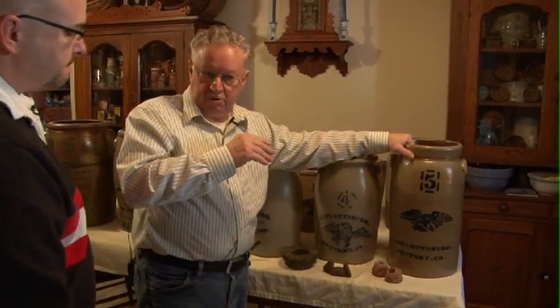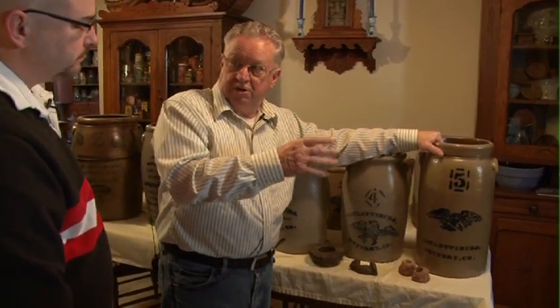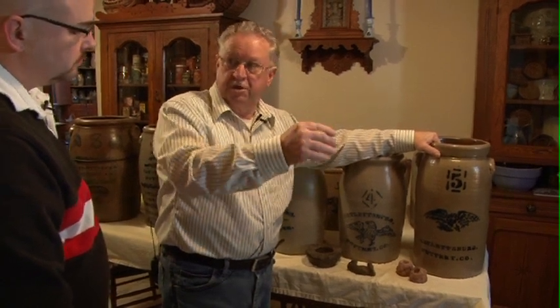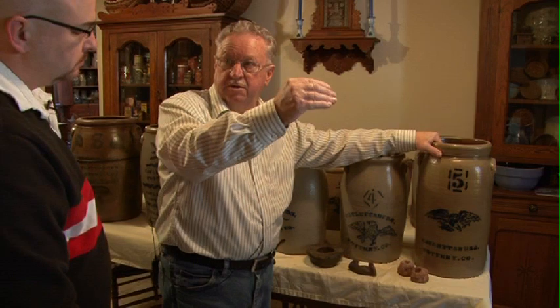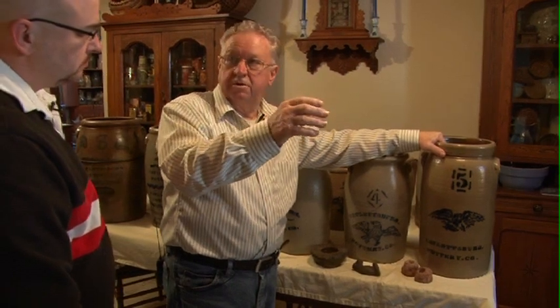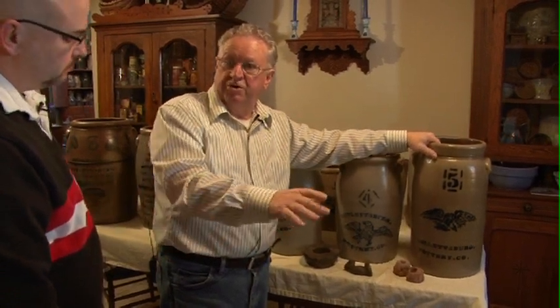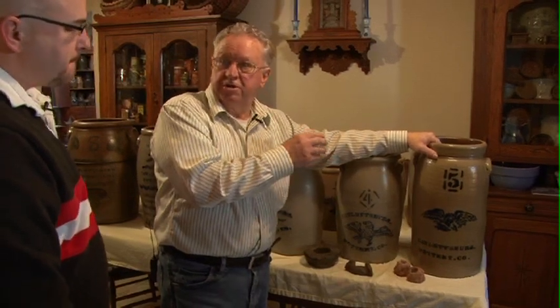It took about a week for them to start, once the pottery was made, to start the kiln as far as the heat. It had already been stacked, and then they would take it up to that degree of heat gradually. And then once it got up to that 2100 degrees, they would introduce the salt into the fire, and when that would solidify and come down, just like dew of the evening, you go out to your automobile and you feel the dew where it's settled. Right. Well, that's what the salt did, and it gave it that salt glaze, that shine.